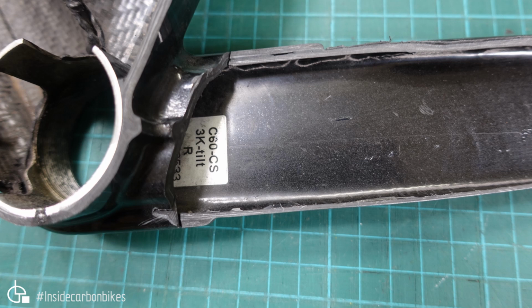Down to the chainstay bottom bracket junction. So when we did look at the bottom bracket, we saw that void there. I mean, it's a reasonably sized void. Will it affect the overall strength significantly? Probably not, just because we've got so much bond area. It's nowhere near the edge, so it's pretty isolated. So it's not really that much of a concern, that one. That one will probably pass.